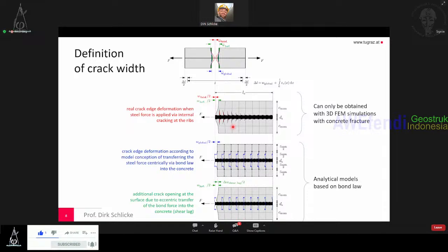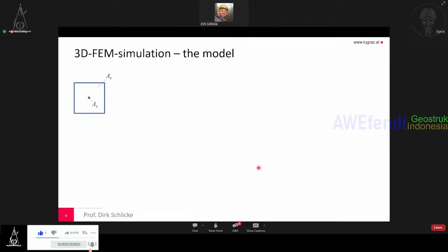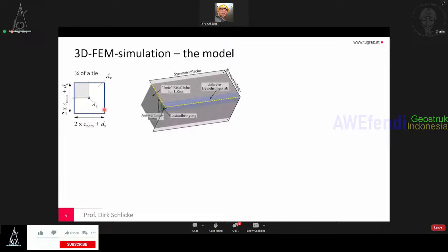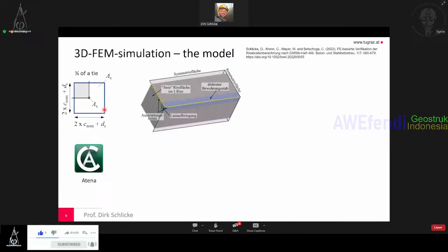I mean, of course, you can also put this in a 3D model with a bar, and you put the spring interface between this, and then you can also simulate this, but you can also represent it with the analytical solution. We made these 3D FEM simulations of the model for a tie. You see a reinforcement bar in the middle and a rectangular concrete cross section around it. The size of the cross section is 2 times the concrete cover plus the reinforcement diameter. And in terms of savings for computational costs, we used only a quarter of the model. It looks a bit like this and was done with ATENA and also published, however, only in German, unfortunately, but I will help you through this.